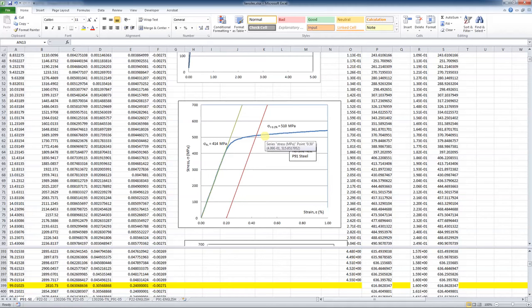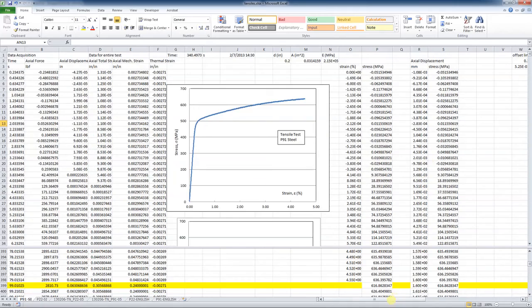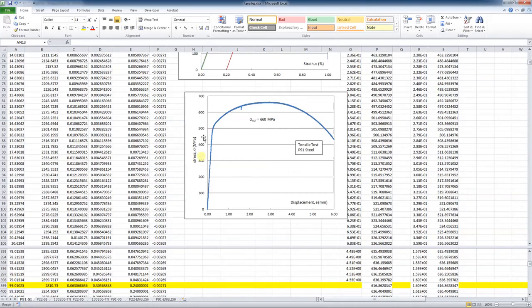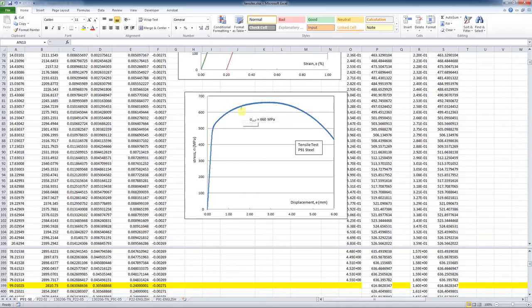What we're going to put into Abaqus will be different from those numbers. Our initial yield stress for Abaqus will be where there is approximately zero plastic strain. I'll give this data to you directly. This plot shows stress versus displacement of the piston — it was a dog bone specimen so you can't use this as a stress-strain curve directly. The ultimate stress was around 660 megapascals, with a small dip around 633 megapascals.